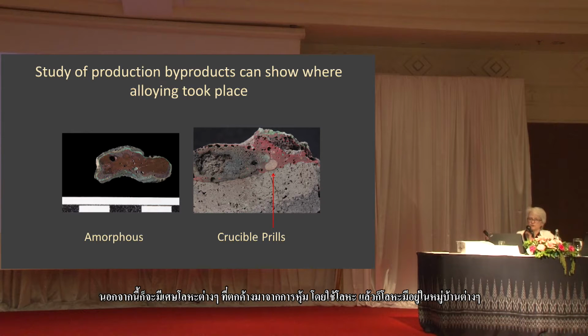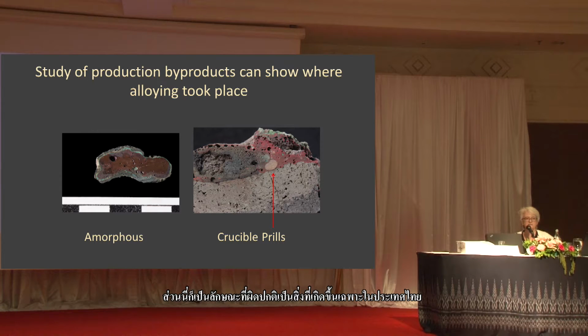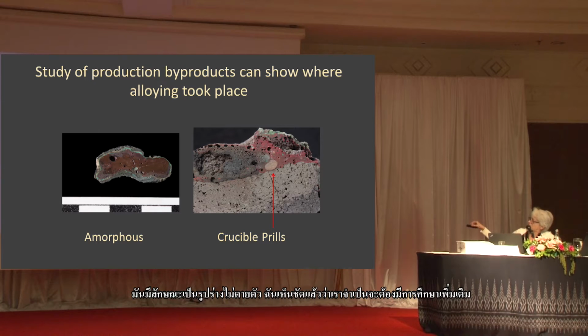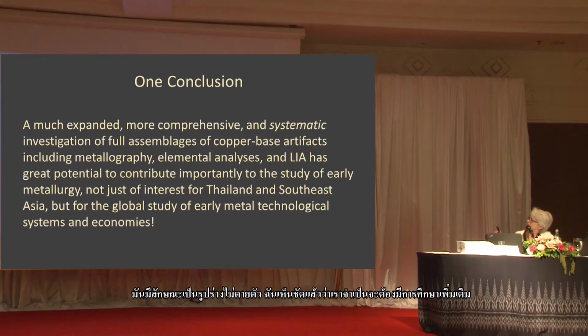And I told you I was going to show you prills. So also in crucibles, you can study the remnants of the metal stuck in the slag and find out where they were alloying. And we believe they're actually doing some of the alloying in the local villages. In fact, the manufacture of final products took place at most local villages. Again, a very unusual aspect of Thailand's archaeometallurgy. This is just a lump of amorphous, which also shows that our amorphous were generally also tin bronze. I'm going to skip that.